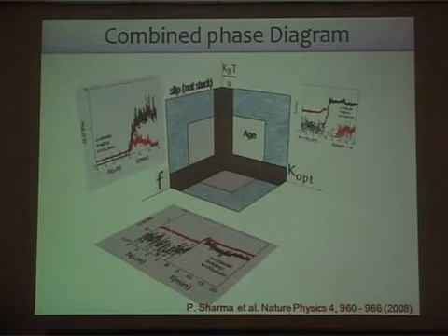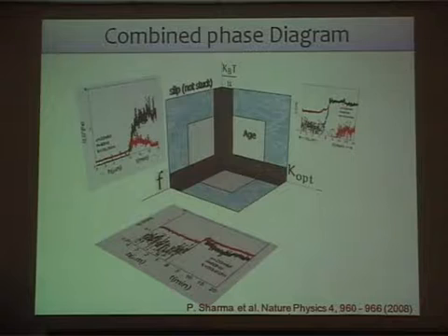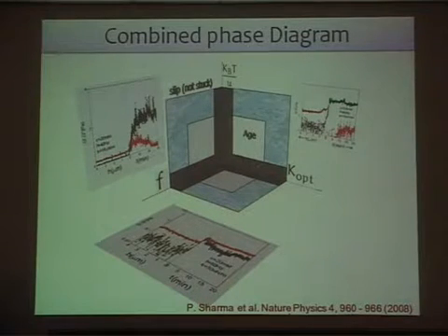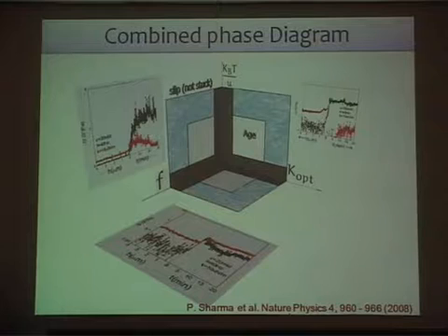So you can make a polystyrene particle behave like a silica particle somewhere up here, which depends upon the salt concentration. If I have high salt concentration, low frequency, low trap strength, then I can make a particle behave exactly like a silica particle. If I take intermediate conditions, then I can make the polystyrene particle age. And if I take still more drastic conditions, in which I have a large drive on the system, very low salt concentration, and a large frequency, then the polystyrene particle will never get to the plate, stuck to the plate.